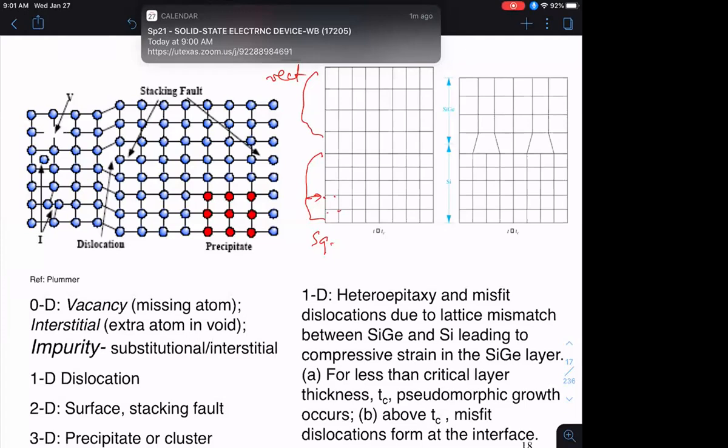And although a square is a special case of a rectangle, since a square has additional symmetry where these two vectors, which are called the primitive vectors A and B, are equal to each other, while in the rectangle they are not, you call a square a different type of lattice because these additional symmetries, we'll see, have implications for the electronic and optical properties of the semiconductor.